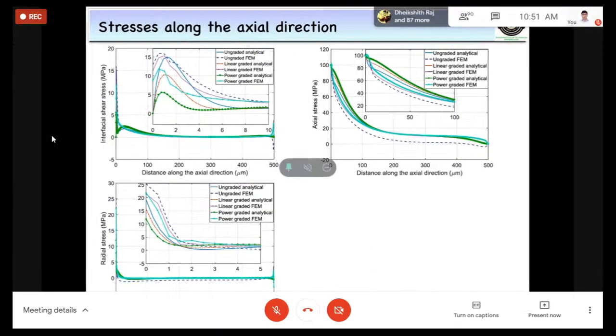So again, the grading plays an important role even in the radial stresses as well. Although the drop is not that significant, the interfacial shear stresses show quite a significant drop, and that's the main purpose. The interfacial shear stresses decide the debonding.